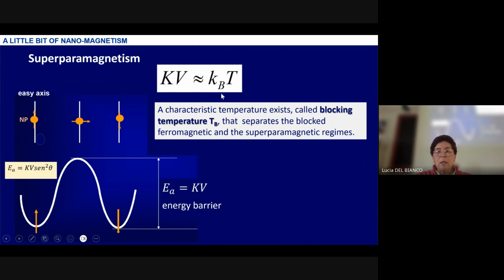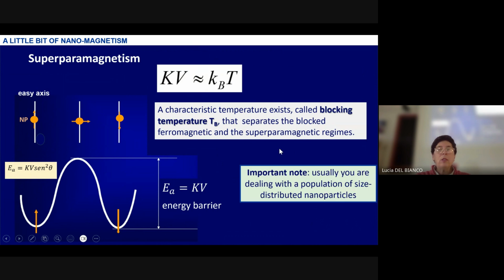So if one looks at this condition, it's clear that a characteristic temperature exists, which is called blocking temperature, that separates the blocked regime, namely the regime in which the magnetic moments can point only up or down, and the superparamagnetic regime in which the magnetic moment is flipping in any direction randomly. An important note is that usually you are not dealing with just one nanoparticle, but you are considering a population of nanoparticles. And even if your nanoparticles are very good, they are never all identical, but they are distributed in size. And this means that you have a distribution of volume, and therefore you have a distribution of blocking temperature, okay?